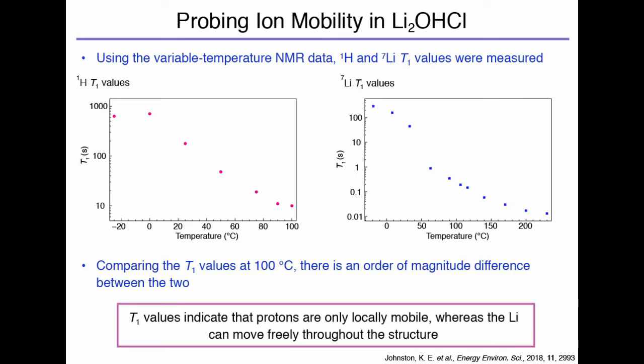And in terms of NMR, what that generally tells us is that there's two different types of mobility. It's suggesting that the protons are only locally mobile, for example, moving around a point, whereas the lithium must be free to move throughout the structure. So if this was to be considered as a solid electrolyte material, it has the potential to have lithium mobility and lithium movement.